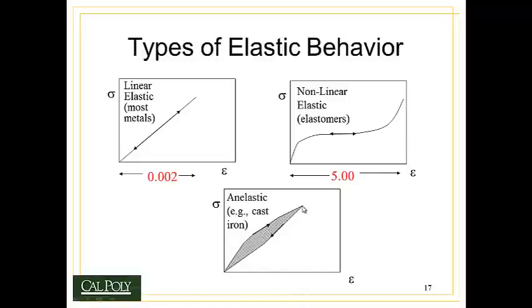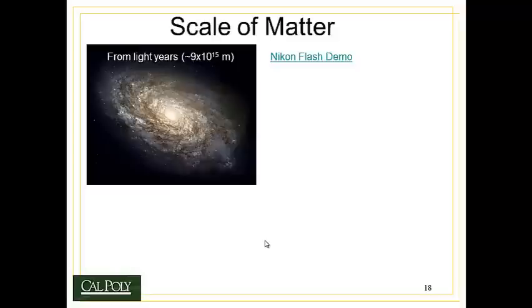The last category of elastic materials is called anelastic behavior. In anelastic behavior, the material's stress versus strain curve follows one shape when being loaded upwards, but when the load is released it follows a different shape. That creates something called a hysteresis loop — a loop between two different directions of behavior. The area inside the loop is the amount of energy stored or dissipated by the material. The area underneath the stress-strain curve equals the energy it takes to deform the material, so it takes more energy to deform going up and less energy when returning. That extra energy is dissipated as heat or noise. So anelastic materials have the ability to absorb vibrations and turn those vibrations into heat — that's why cast iron is used for engine blocks.